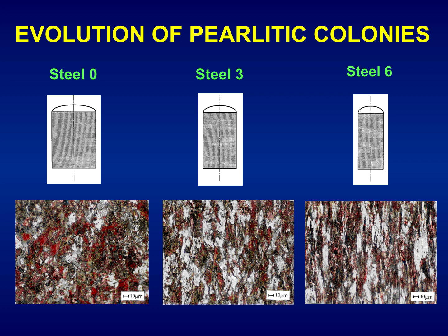While the steel 0 exhibits a randomly oriented microstructure with randomly oriented pearlitic colonies, there is a slight orientation in the vertical direction of the micrographs, cold drawing y-axis direction in steel 3 with an intermediate degree of cold drawing, and finally in steel 6, heavily drawn steel, commercial prestressing steel wire, there is a markedly oriented microstructure regarding pearlitic colonies in a parallel direction to that of cold drawing, y-axis or vertical direction of the micrograph.